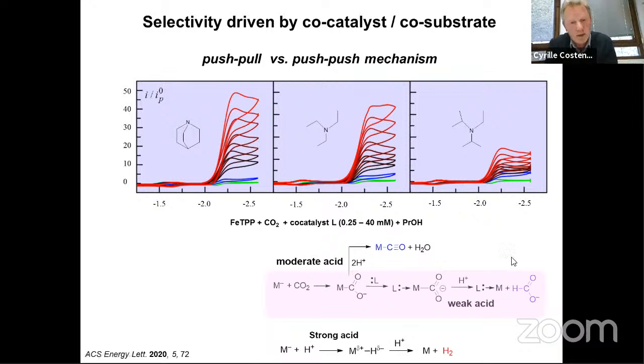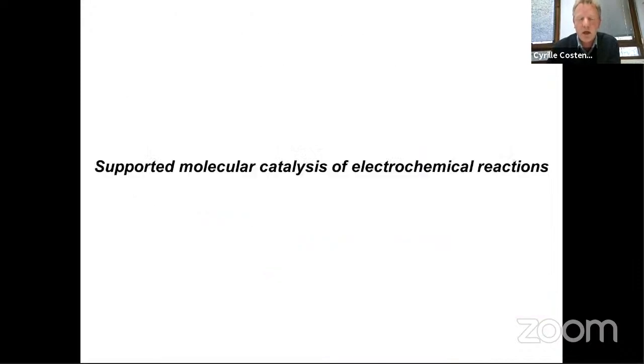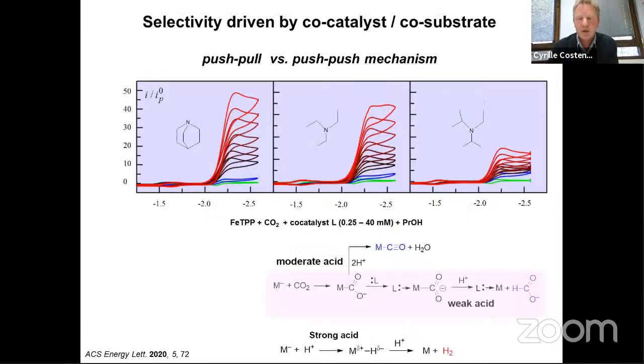So this means that formation of formate does not necessarily go through the formation of a hydride, and this is what we have shown here, just based on the CV analysis and the observation of the product in bulk catalysis, and from the analysis of the CV, where we've shown that addition of base can boost the reduction of CO2 to make formate.